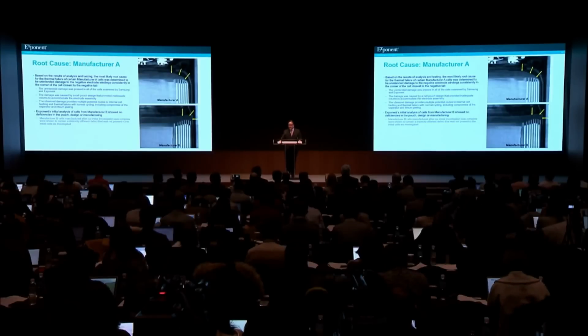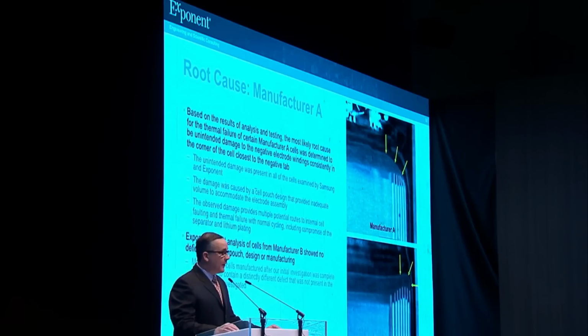As part of this initial work, Exponent was asked to perform an analysis of cells from manufacturer B because they were intended to replace the cells of manufacturer A. Through this analysis, we found that manufacturer B cells did not share the pouch design problem with the cells of manufacturer A, and that the cells available at the time of our investigation were free of other common design or manufacturing defects. Unfortunately, that is not the end of the story for manufacturer B cells. Exponent later found that a new and distinctly different manufacturing defect was present in manufacturer B cells that were manufactured after our initial investigation.